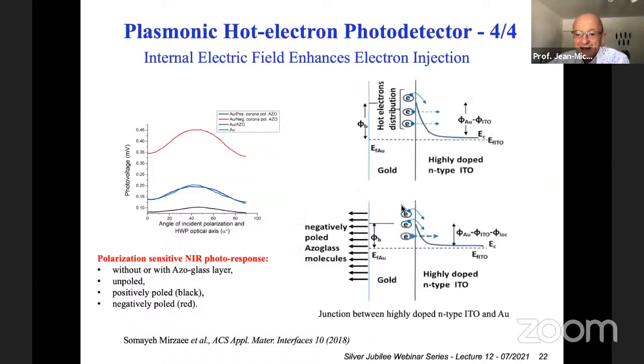To picture what is happening exactly, the gold and the ITO do not have the same Fermi level. When we put them in contact, the Fermi levels get equilibrated because there is no net current flowing through the device. So the two Fermi levels become identical by an exchange of charges, technically an exchange of electrons from the ITO to the gold, because the work function of the gold is larger than the work function of the ITO, larger by typically 0.3 eV with standard materials. So that creates a tunnel barrier for the charges, for the hot electrons to be emitted from the gold, because it is in the gold that the hot electron is emitted, into the ITO.